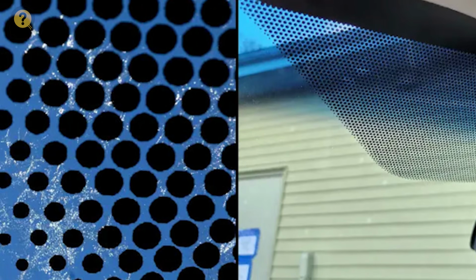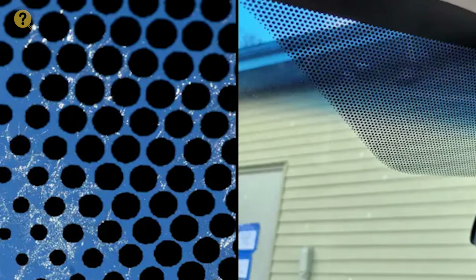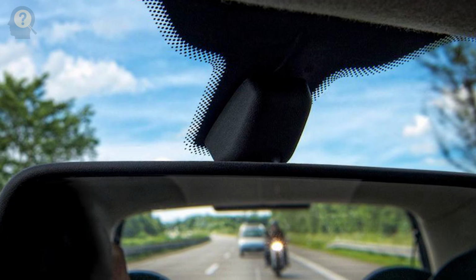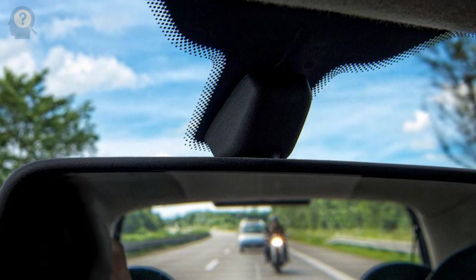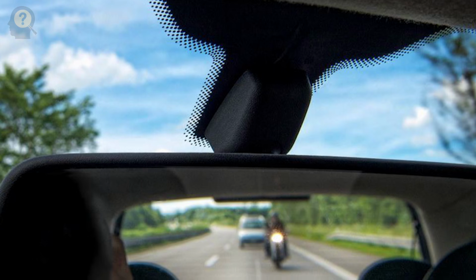The closer you get to solid black, the more heat the glass absorbs. But because the dots get progressively smaller and more spread out as they move toward the clear center, the temperature shift happens across a few inches rather than at one hard edge.